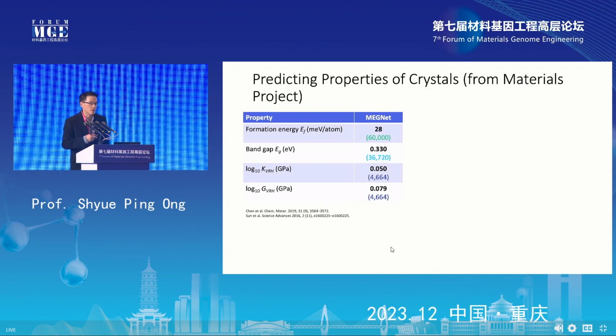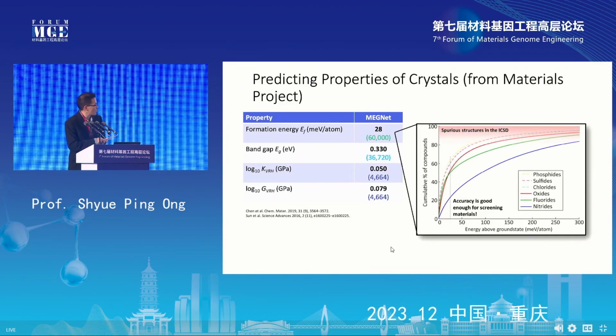But we can already predict things like the formation energy of crystals to within about 28 milli-electron volts per atom or so, okay? We can predict the band gap of materials to within about 0.33 electron volts. We can also make models that can predict things like the bulk and shear modulus of materials, right? Just to illustrate what that 28 milli-electron volts per atom means, okay?